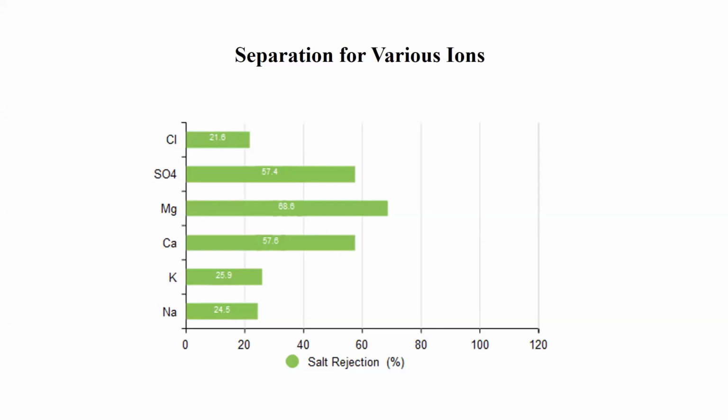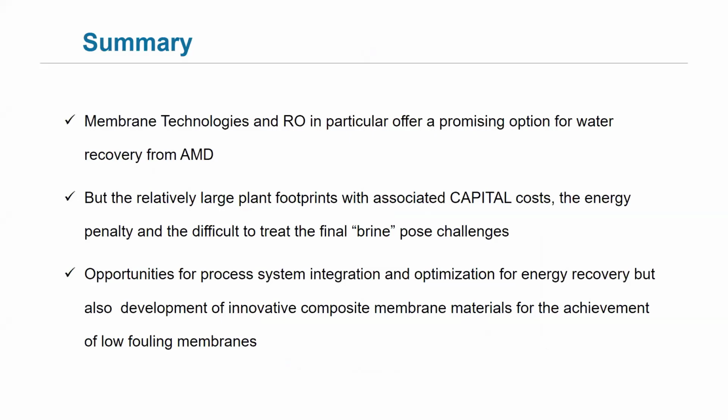So you can see clearly that the membrane was able to remove most of the ions, including the smaller ions like sodium and potassium, which stand at 25, 26%. So this has come to the end of my presentation.